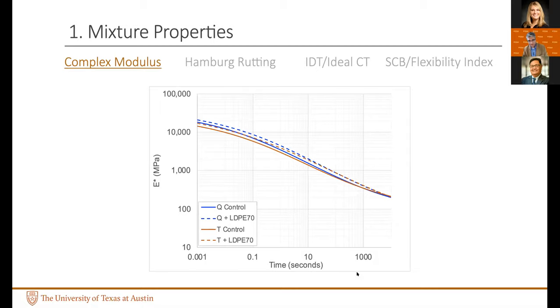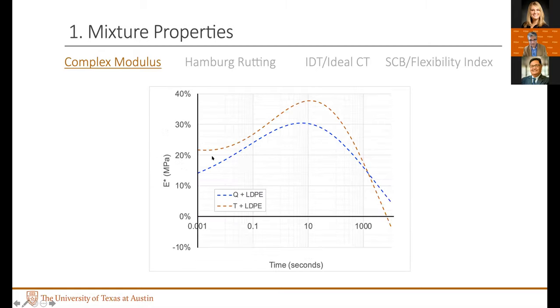You can see the solid lines are the controls, the dashed lines are the LDPE. This is on a log scale, so maybe this is a better picture to look at if you look at the percentage change with respect to the control. So this is not the master curve itself, but percentage change in the master curve. So if you see, both the Qatar and Texas binder showed somewhat similar trends that LDPE sort of had at around 10 seconds in that master curve, which corresponds to a slow rate of loading or somewhat high temperature side, intermediate to high temperature side.